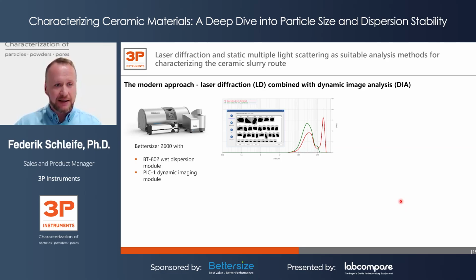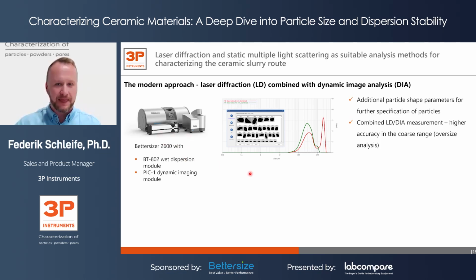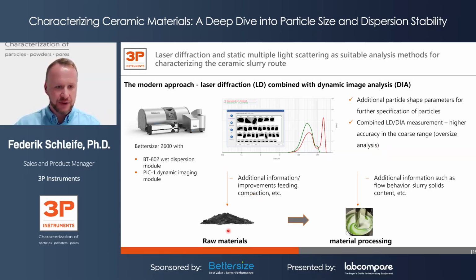And even better, if you combine on a modern approach the laser diffraction with dynamic image analysis, like it can be done with the Bettersize 2600 and the PIC1 imaging module, you get additional particle shape parameters for further specification of your powders and particles. And in a combination of laser diffraction and dynamic image analysis, you can even increase the accuracy in the coarse range, which might show you if there are any oversized particles in there. So again, it works pretty well for the raw material with additional information and improvements for feeding compaction or others. And also you can get additional information for your slurries, like the flow behavior, the slurry solid content, and others.